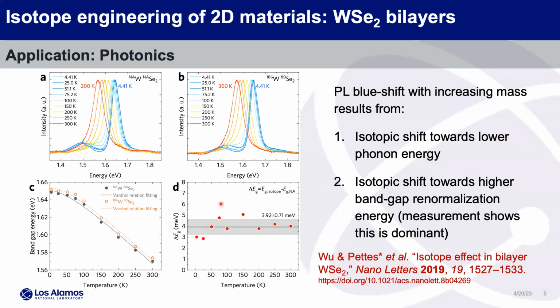So we see this change is a direct effect of that band gap renormalization that comes about because of this isotopic shift. And this is small, right? This is going from natural to 186, so it's a little over 1 neutron that we're changing. But it was pretty significant, and we were pretty happy.